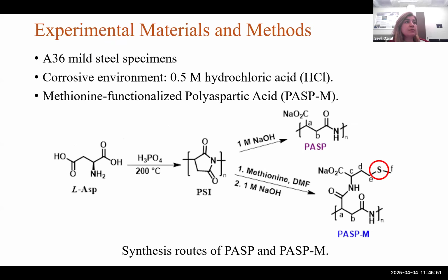Here is the experimental part. For the materials, we use steel specimens, A36 steel type, and we synthesize the methionine functionalized polyaspartic acid. It's a very straightforward synthesis process. It starts with aspartic acid, which is one of the amino acids, and then polyaspartic acid. We selected polyaspartic acid because it has a long chain structure and multiple adsorption sites to provide better inhibition of corrosion.